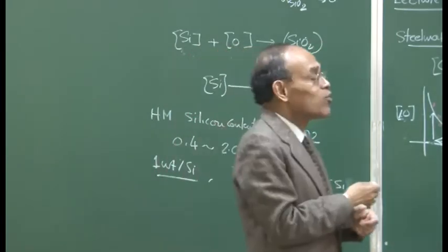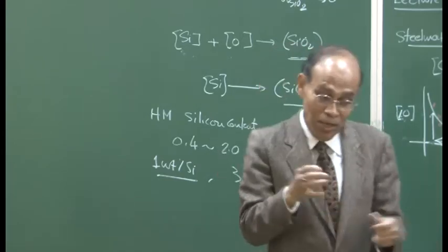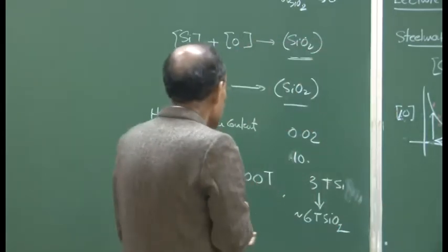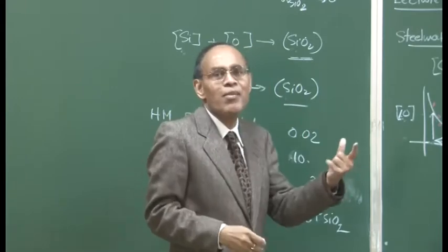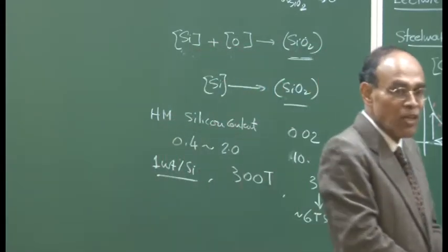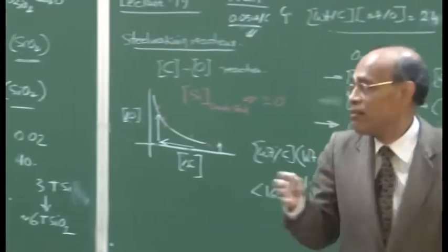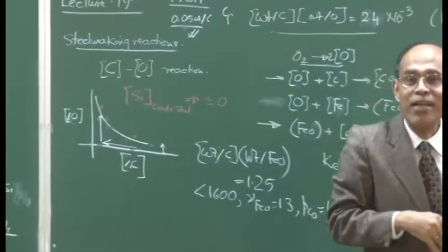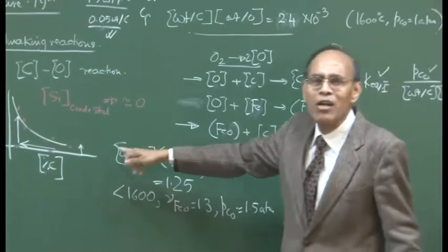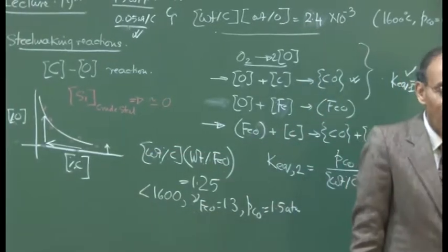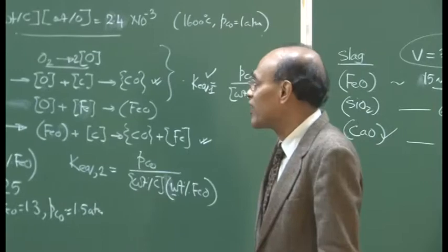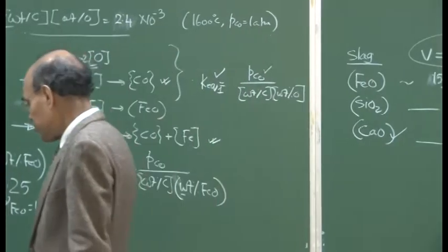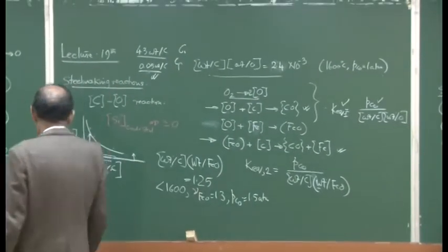And we will see why the oxygen steel making converter has become popular, particularly when you analyze the rate of the reaction. So, I would say that in an oxygen steel making converter, within the first 2-3 minutes itself, all the silicon in the bath is going to be completely eliminated. But the total elimination of carbon is going to take some amount of time, particularly as the decarburization rate falls as a function of time.